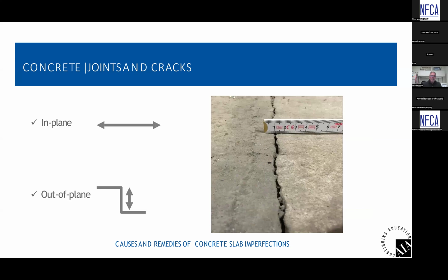So there are a couple of different types of cracks that you see out there. In plane is where there is a crack in the concrete, but at the same elevation. But the most concerning would be an out of plane crack, and that's where one side of the crack is higher than the other. That's a dead giveaway of some sort of structural movement just about every time. So any out of plane cracking, by all means, raise the red flag.